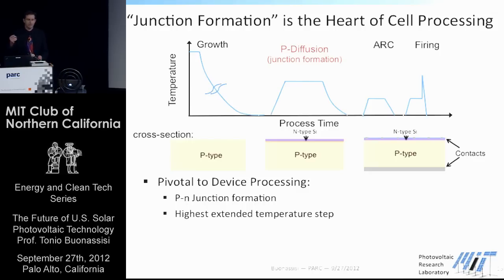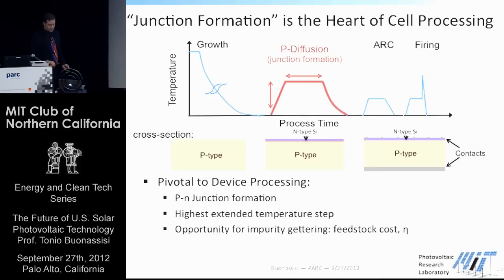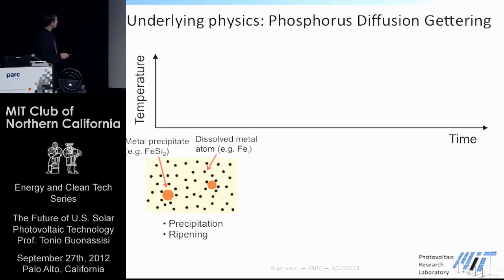of the material. And just like sugar inside of your coffee has a higher solid solubility when the temperature is higher, and as the coffee begins to cool, the sugar begins to precipitate out in crystalline form. A similar effect happens here where the metals dissolved or precipitated out inside of the material begin dissolving as you heat your wafer up. And so to understand that in a better form, we take the cross-section of our device, and now we're populating it with precipitates of iron and point defects, little black dots, individual iron atoms moving around the lattice, so-called iron interstitials.